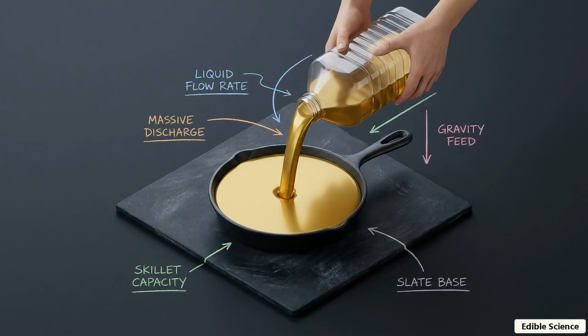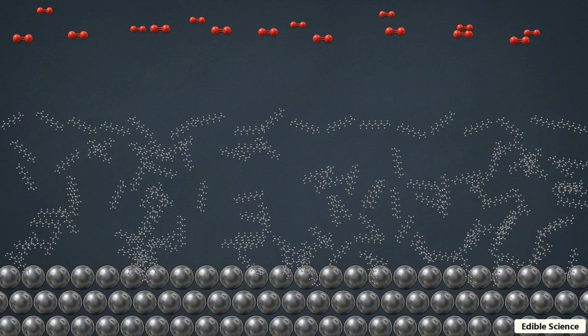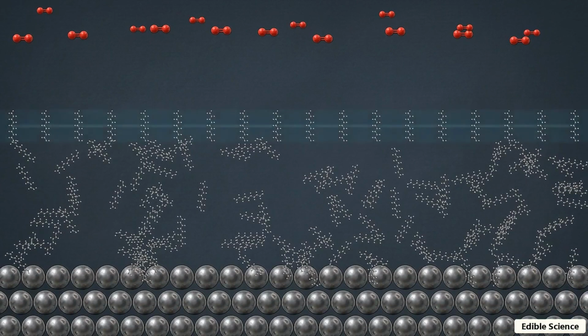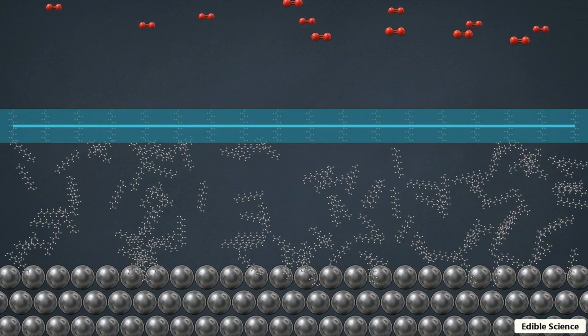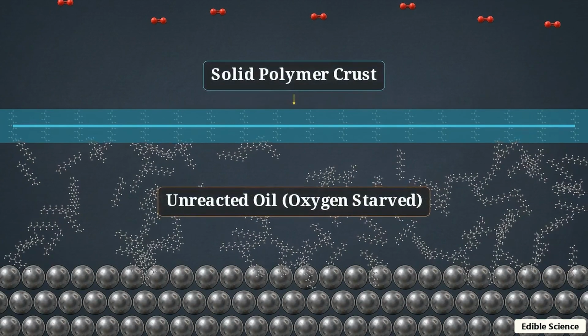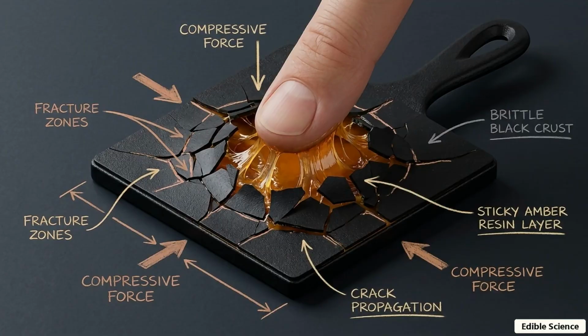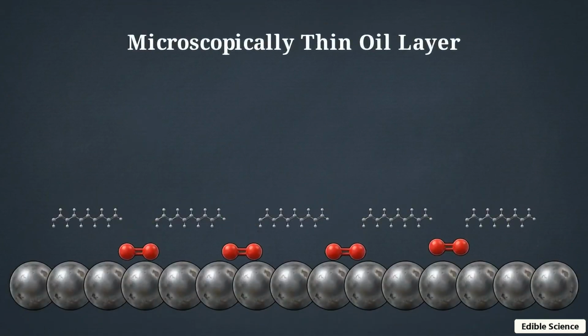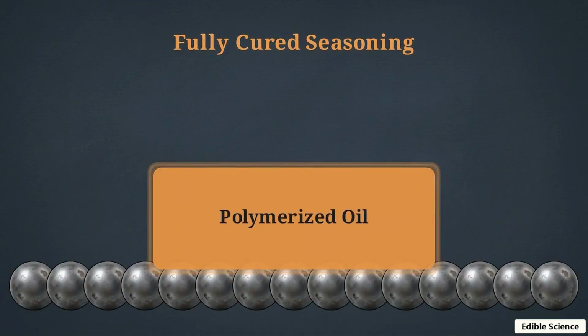This requirement for oxygen reveals why the intuitive attempt to season a pan with a thick layer of oil often fails. Many assume that a thick puddle of oil will yield a superior heavy-duty layer. In a thick puddle, the top surface of the oil cross-links and hardens almost immediately. This creates a solid physical barrier that causes descending oxygen molecules to bounce off. By blocking the atmosphere, the deeper oil is permanently starved of oxygen. It never finishes reacting, leaving a sticky, gummy mess trapped beneath a thin, hard shell. Wiping the pan until it appears dry is a strict geometric requirement. The film must be microscopically thin to ensure total polymerization of the entire layer.